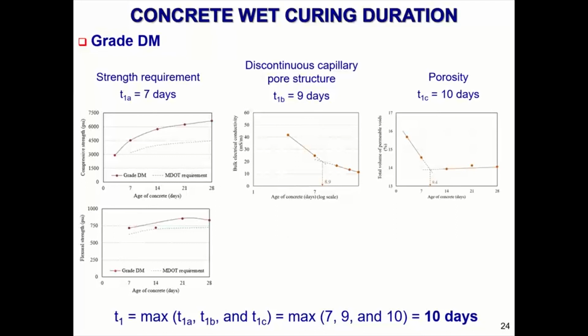They first looked at wet curing duration for our grade DM concrete. So you'd want to make sure that this would be the minimum at which we could apply an overlay. To meet the strength was 7 days. To meet the discontinuous capillary pore structure took 9 days of wet curing, and to meet the porosity, it took 10 days of wet curing.